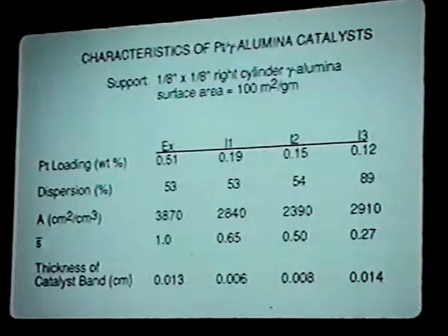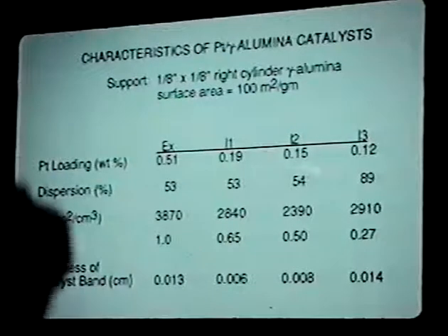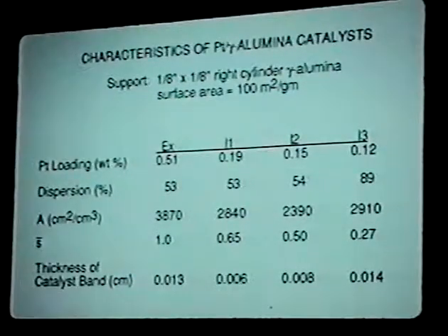Then the internal catalysts we put into a second impregnation step with the citric acid to push the platinum band inside the particle. But we didn't do that for the external catalyst. That's why it retains most of the platinum that was adsorbed onto the particle, whereas the others may have had platinum dissolved from the particle, which retains less platinum in the catalyst.